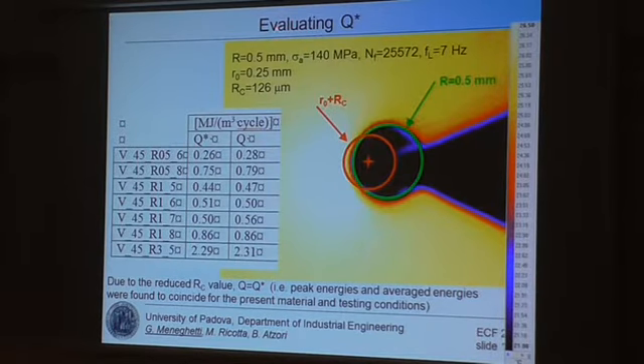Now I would like to comment on the value of Q star, which is the energy dissipated inside this slice-shaped structural volume. If you compare the values of Q star, which is the mean thermal value inside the structural volume, with the maximum value, you see that the two values are more or less equal. The maximum difference observed was about 10%. Now, in this case, for the present material and for the size of the structural volume of this material, the two values are very similar. So, in this case, the maximum value of the heat energy dissipated at the notch tip is more or less equal to the mean value.